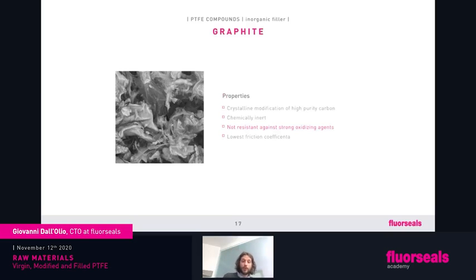Graphite is a crystalline modification of carbon, is more pure, and the shape is a flat shape. Graphite is widely used for its dry lubricant properties. Basically, graphite will help reduce the friction on dry dynamic application. Because when we do have a sliding application and dynamic application, and we have to have a very good wear, but we do also need some lubricants. So one of the most common can be glass plus graphite, because you will have the improved performance of wear thanks to the glass, but the lubricity, the friction behavior will be great thanks to the graphite.